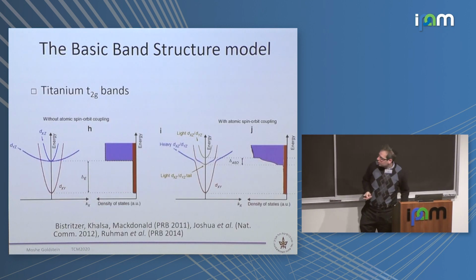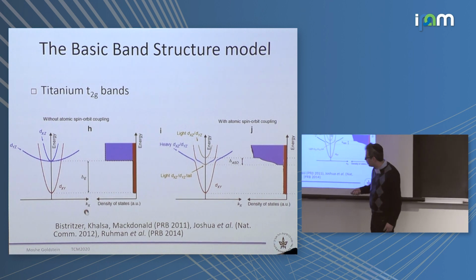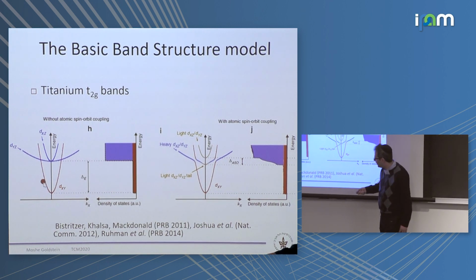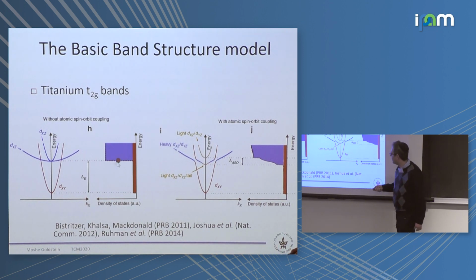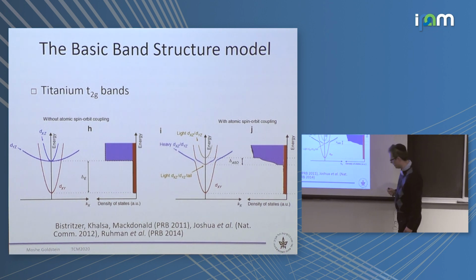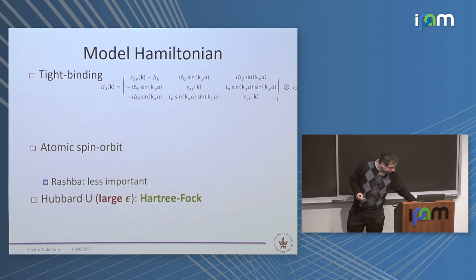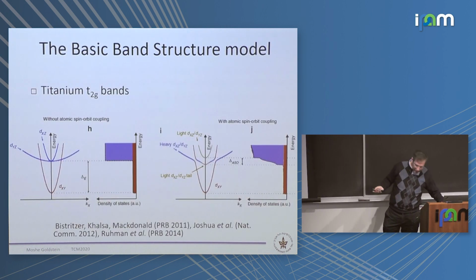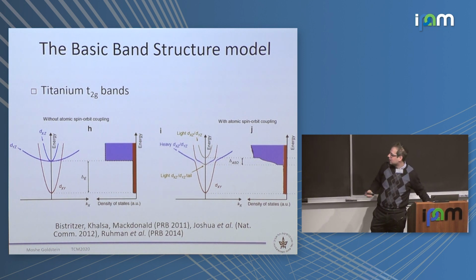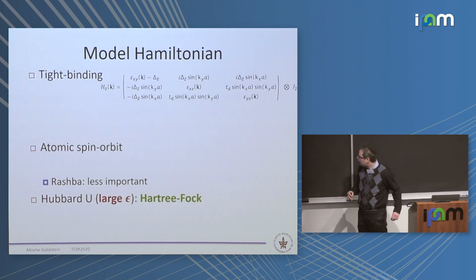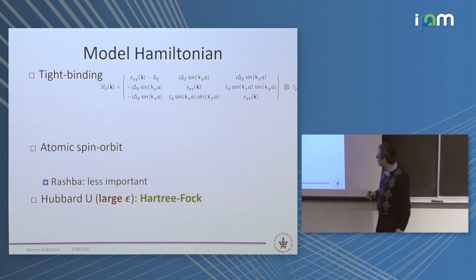And then, so this is a typical picture. First you have the xy with low mass in the xy, and it's lower in energy at the interface, and then the other bands which have high mass, higher density of states. But the bands are mixed and coupled by different things, and then it becomes a bit more complicated. So we need to take that into account. So we basically write down a model based on those earlier works, which are themselves some tight binding modeling of ab initio data and also of experimental results. So this is going to be our Hamiltonian. I'm going to write the different terms.